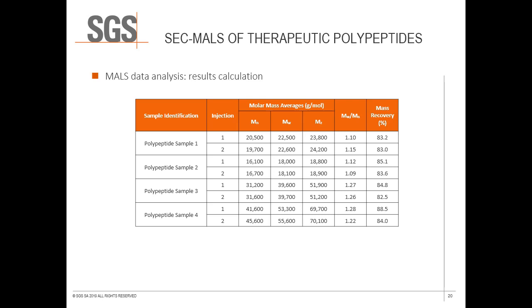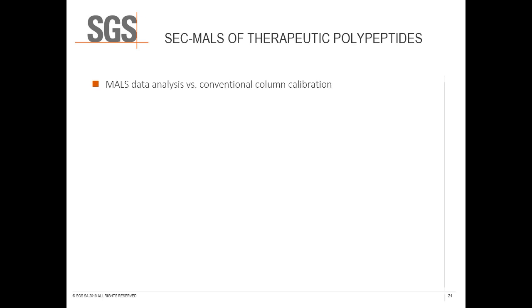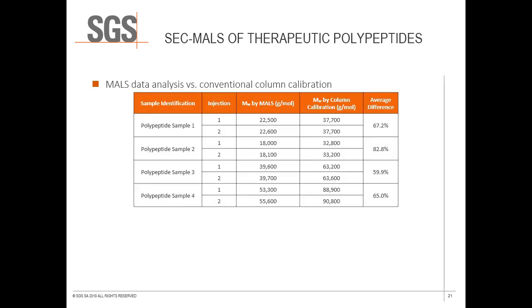This is notable due to the effect this will have on the accuracy of calculated number and z-average molar masses. The Mw, or weight average molar mass, is directly measured by light scattering analysis and is independent of the effectiveness of the chromatographic separation. The number average and Z-average molar mass values are calculated based on molar mass and concentration values for each slice across the chromatographic peak. Therefore, the accuracy of Mn and Mz are strongly dependent on the separation. For this particular set of samples, results were also calculated using conventional column calibration.